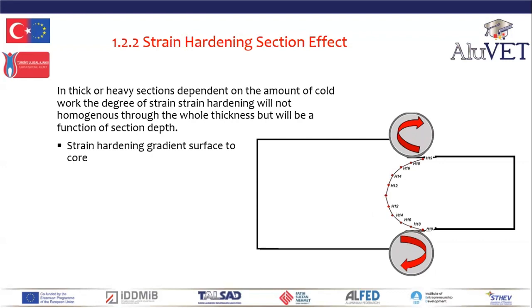During work hardening of thick or heavy sections, the surface will be subjected to a much greater deformation than that experienced in the center. So we will see work hardening of the surfaces not being fully transmitted to the core. So there will be strain hardening gradients from surface to core. The surface might be H18, but the core may only be H14.